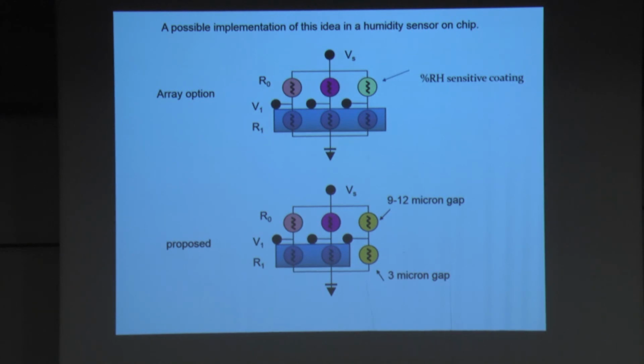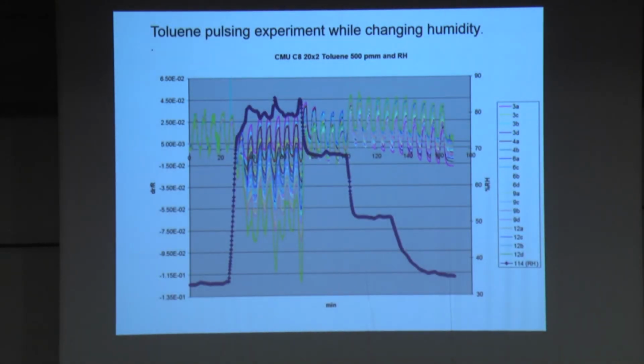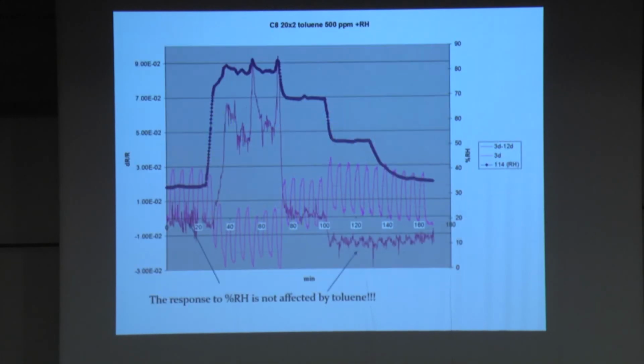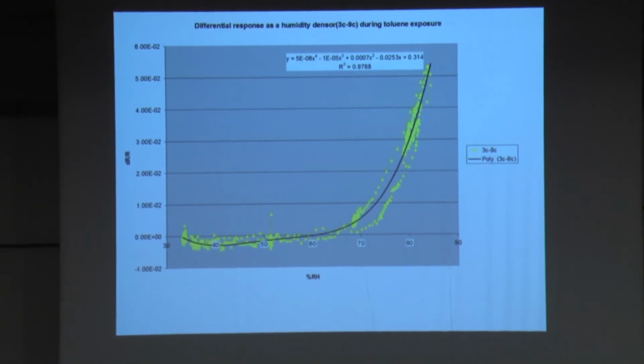And what we did, we took the system and subjected it to 500 ppm pulses of toluene, 2 minutes on, 2 minutes off, while changing the relative humidity. Okay? And what we got is that, here is the response of the 3 micron sensor. This one is the humidity change, and this line in here is the response of the sensor. Look here, when the humidity doesn't change much, you barely see any toluene response. Same thing here, which means that this sensor can act very nicely as a humidity sensor, even at very high concentrations of other solvents.